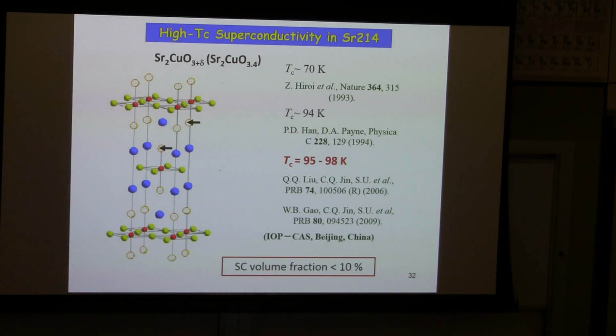Okay, skip on. But we are still hoping, or there is some evidence, that we can expect a much higher TC. That is the strontium counterpart, strontium 214, Sr2CuO3+δ. That had long been known since 1993 again. The highest TC realized in this strontium 214 material is 98K. This is the highest TC among the known single layer high TC cuprates.